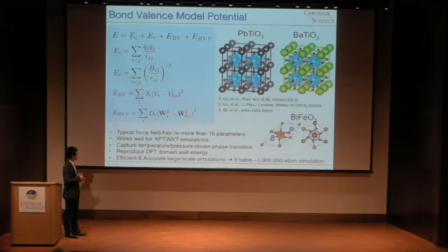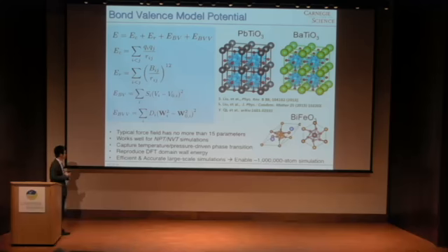They work well under both constant pressure and constant volume conditions. They can capture temperature and pressure-driven phase transitions. They reproduce DFT domain wall energy pretty well. All these energy terms can be computed pairwise efficiently. This enables million atom simulation at nanosecond timescale, as demonstrated in yesterday's presentation.